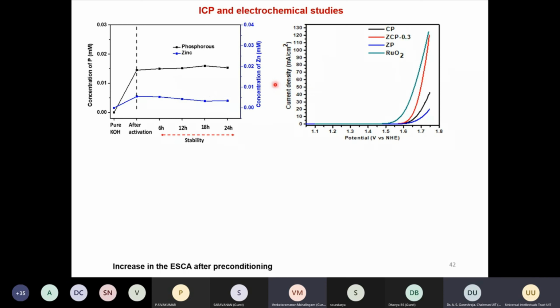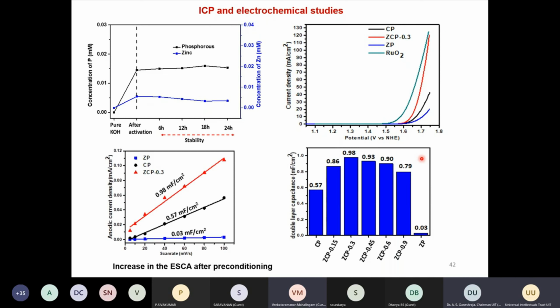So here I have shown the activity of this material towards the oxygen evolution reaction. Here again we compared with ruthenium oxide, and we found that the ruthenium oxide is better, but our material is very close, particularly at a higher current density. You see this is very close to that of the ruthenium oxide that is used commercially.